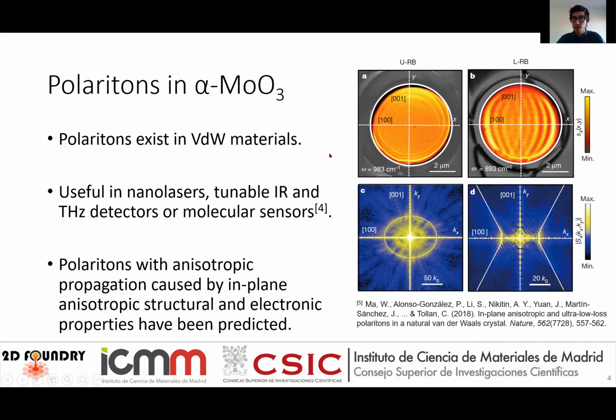For example, here two kinds of modes of this material are studied: the upper Reststrahlen band, which is 983 cm^-1, and the 893 cm^-1 Reststrahlen band modes. And this is a technique used by Alonso González et al., which is called scattering-type scanning near-field optical microscopy, in which a metallized AFM tip is illuminated with polarized light, and you can measure the polaritons.